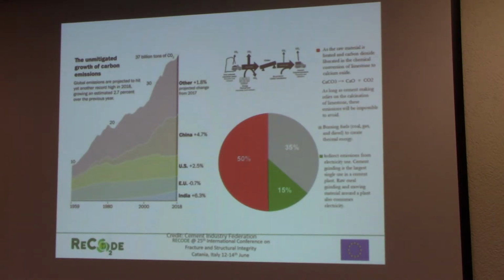Probably you know that in the cement factory plants, the CO2 emissions are mostly related to the process that transforms the limestone in calcium oxide via the calcination process. And this calcination process accounts for 50% of CO2 emissions. And it's important to highlight that these kinds of CO2 emissions are very difficult to eliminate. The 35% of CO2 emissions are related to the burning fuels, and the remaining 15% are indirect emissions in atmosphere that are widely related to the grinding phases and to the transportation of the materials out of the cement plant.